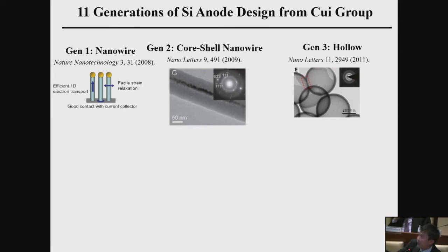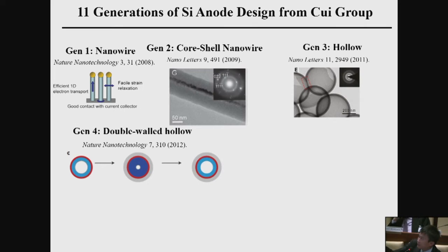So in order to build a stable interface, several years ago, my group came up with an idea. I think this is a universal concept now. How do you solve this problem of instability of the interface? Let's look at generation 4. We have actually a double-wall hollow structure. The blue color is silicon. Outside is a mechanically strong layer. Once lithium comes in, volume expansion, you actually make it expand towards the inside instead of outside. You leave empty space inside, so it doesn't push outside. You build a stable interface facing the electrolyte. Now your battery becomes very stable. So we showed that in this publication. I consider that a very important milestone in battery research.